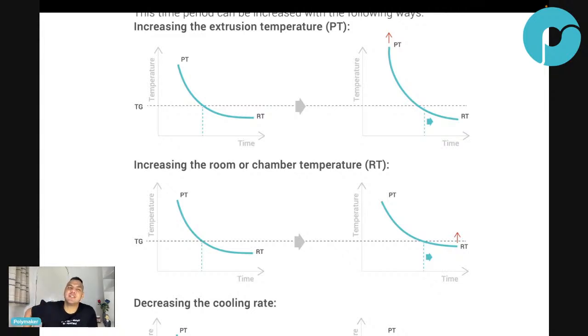But that doesn't matter, because the first layer you print will have the same cooling rate whether you print fast or you print slow. No. Let me think. If you print fast, does that increase the time the layer is going to spend above Tg? If you print fast, so if you compare to print slower... no. If you print fast is worse, because let's say you print at 260 degrees, right? You print slowly. If you print slowly, then the heat is going to diffuse more.